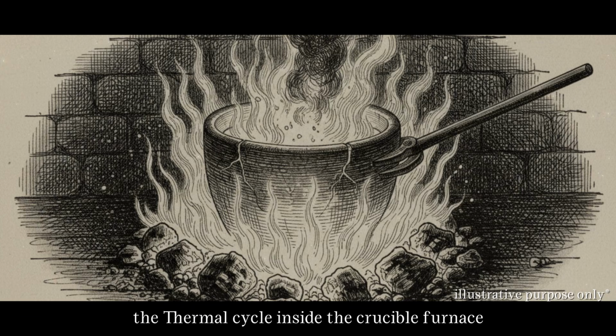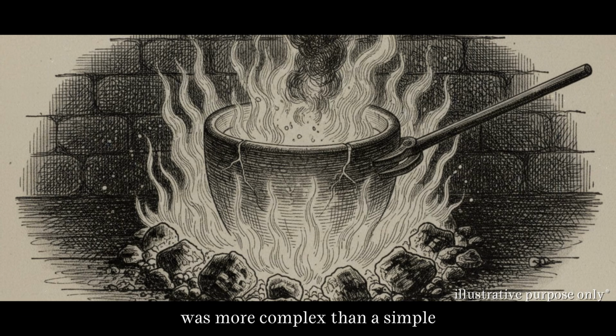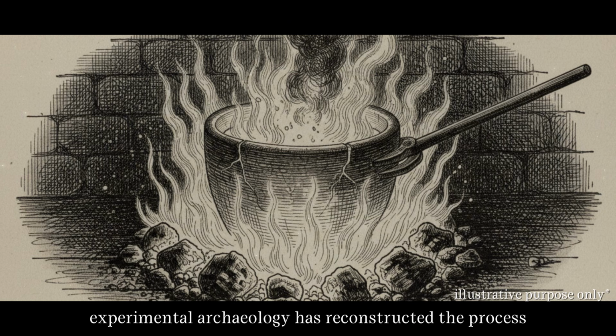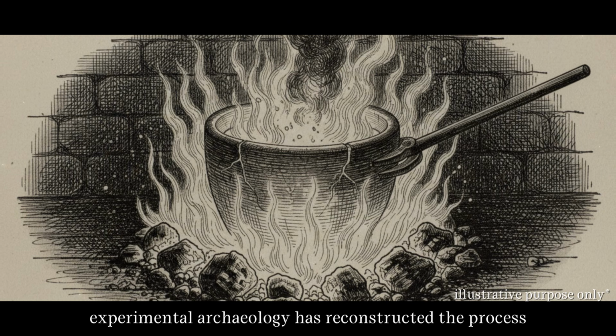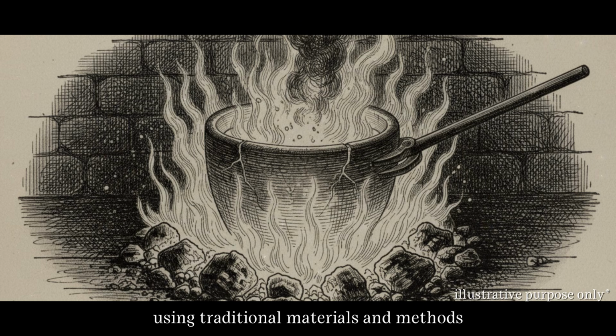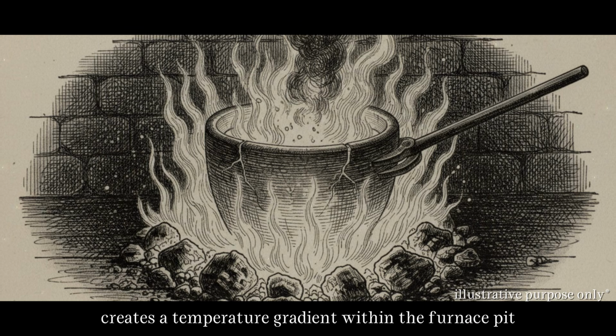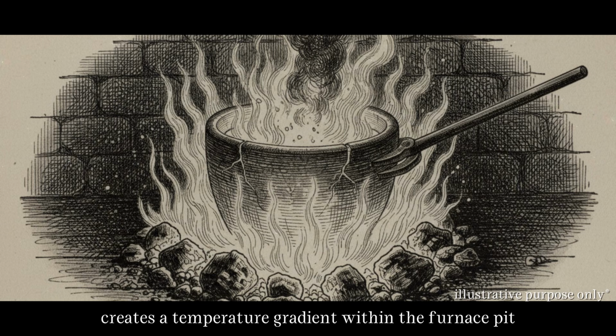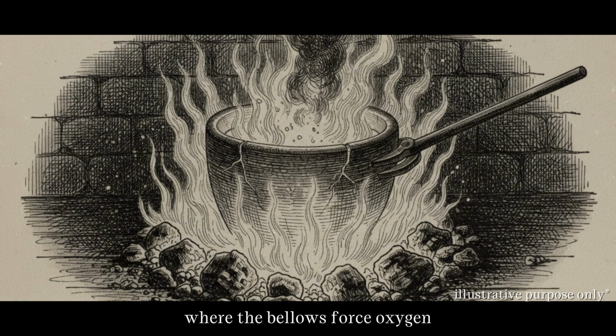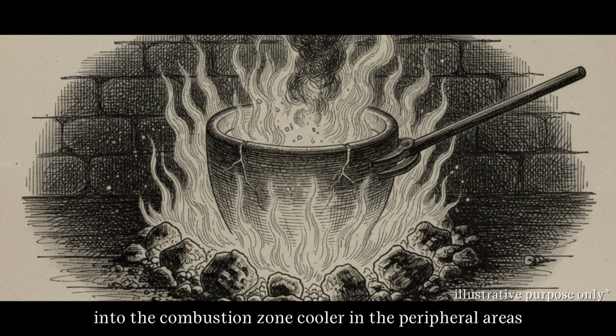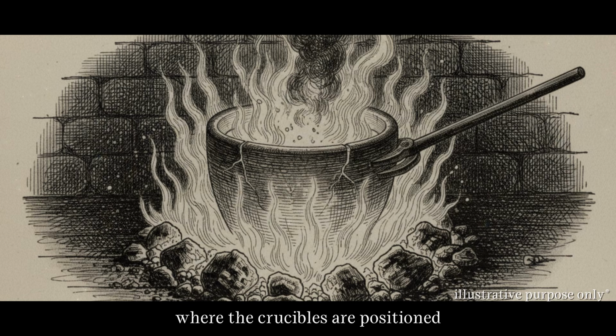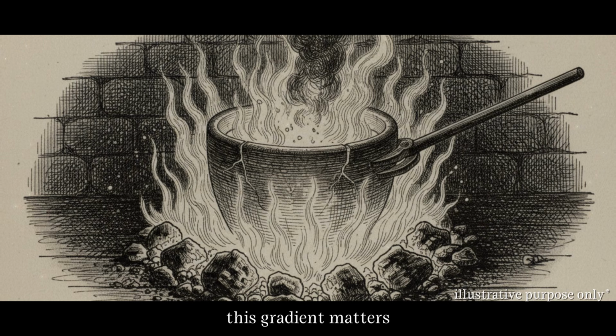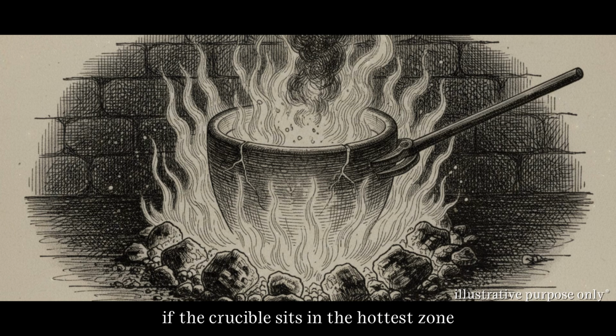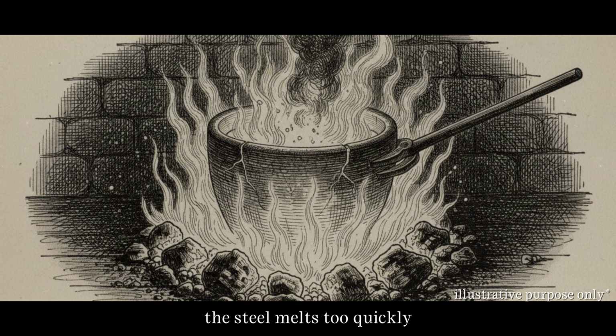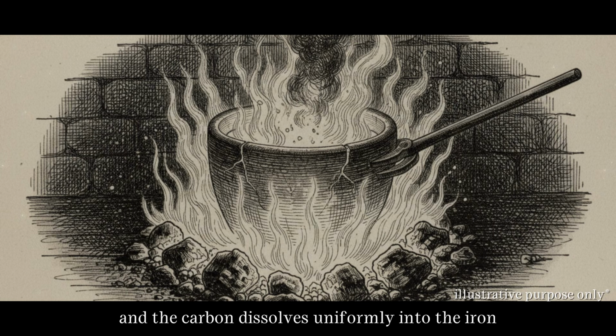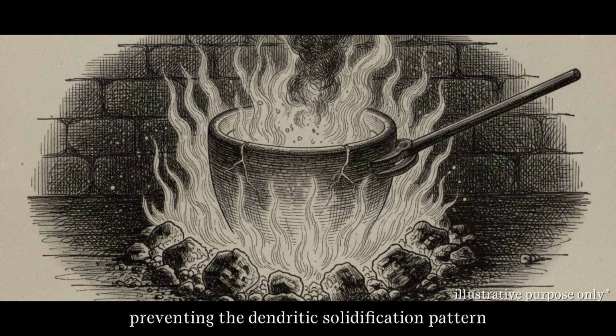The thermal cycle inside the crucible furnace was more complex than a simple heating and cooling curve. Experimental archaeology has reconstructed the process using traditional materials and methods. The charcoal fire creates a temperature gradient within the furnace pit, hotter near the air inlet where the bellows force oxygen into the combustion zone, cooler in the peripheral areas where the crucibles are positioned. This gradient matters. If the crucible sits in the hottest zone, the steel melts too quickly and the carbon dissolves uniformly into the iron, preventing the dendritic solidification pattern.